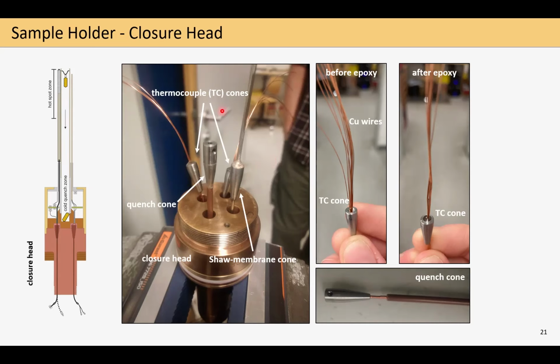And we have normally attached there two thermocouple cones, one quench cone, which looks in detail like this, which we need to quench our experiments, and then this supplementary Shaw membrane cone, which is part of the hydrogen system. And these cones are then just sealed into the closure head again with epoxy resin. And it's holding pressure. I'm still astonished after all these years in Hanover.